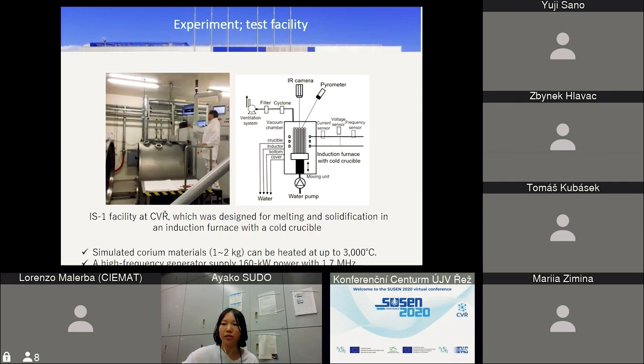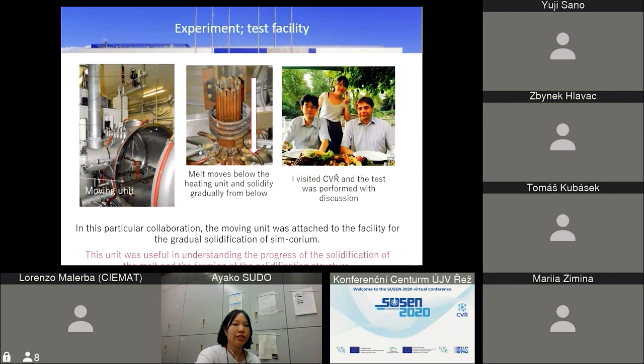This large-scale heating system is so useful to simulate the solidification of 1F conditions. And additionally, in this particular collaboration test, a moving unit was attached to the facility for the gradual solidification of simulated corium. Using this moving unit, the melt in sample stage moves below the heating unit slowly and solidifies gradually from below. It means this unit was useful in understanding of progress of the solidification of the melt and the forming of the solidification structure. It means it's useful to understand where is the final solidification of melt or where is the later solidification area of a melt. And in 2016, I visited CVR, and the test was performed with discussion with CVR experts.